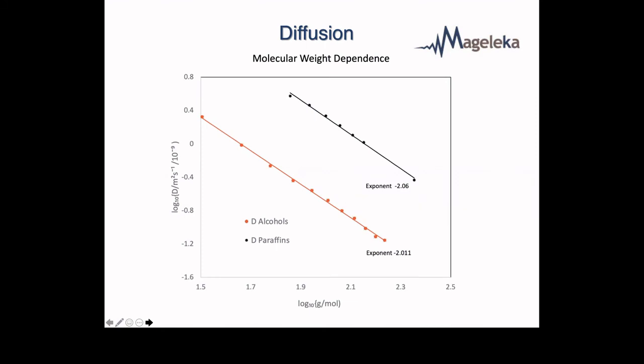This is just some test experiments we did when we were putting the machine together. So this is the diffusion coefficient of alcohols as a function of molecular weight and paraffins. And you get a nice straight line using a power law. And the exponent of this is -2.